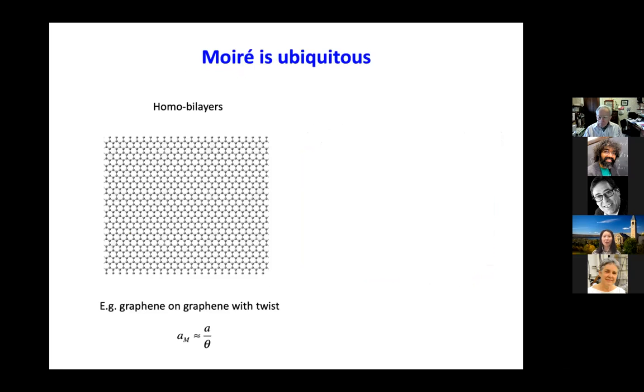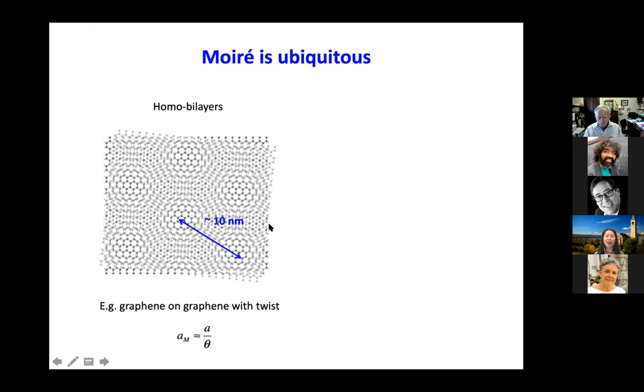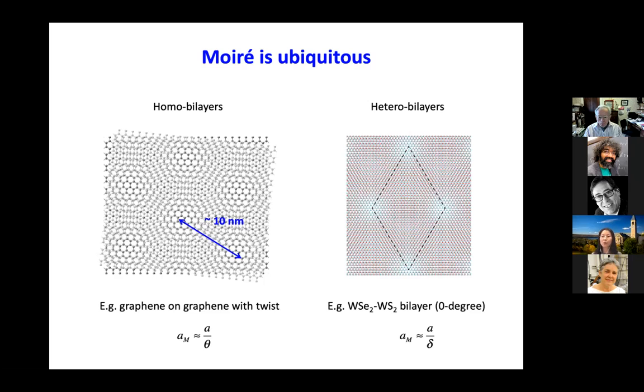And today, what I'm going to talk about is something of a new kid on the block, this Moiré system. So I'm sure you have seen something like this many, many times. We have 1 sheet of graphene, and then if you bring in another sheet with a little bit of twist, then you generate this interference pattern, which we call Moiré, right? In this particular case, you can see the period is on the order of 10 nanometers. So it's like 20 or 30 real lattice sites. Or you can get the Moiré pattern by putting 2 sheets of slightly different material with a few percent of lattice mismatch between those 2 semiconductors. You also get a Moiré pattern, and the period is also on the order of 10 nanometers.